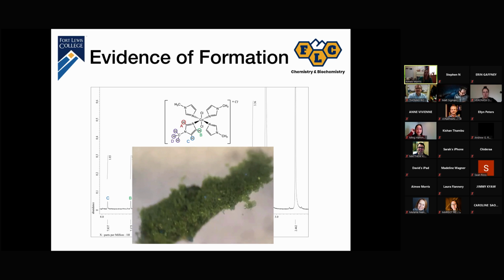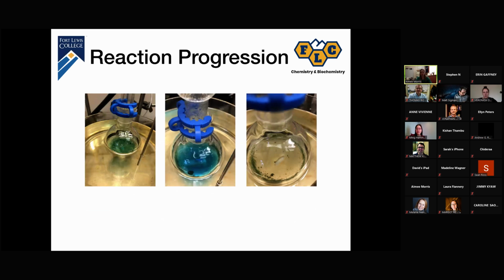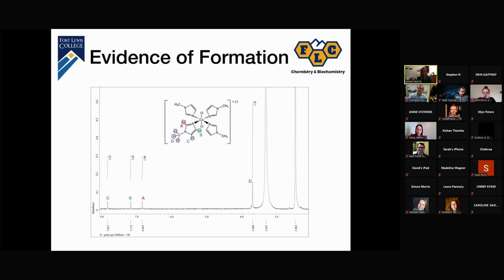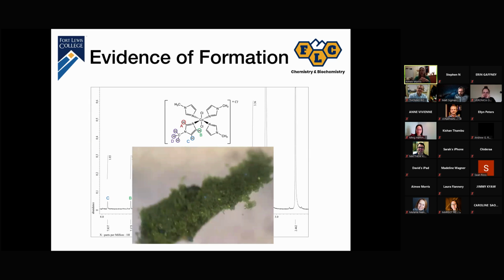And so this is a beautiful reaction, by the way, and students love to run reactions in my lab because they're highly colored. The very first round bottom you're seeing, the cobalt pyridine complex that we start with, is a very glittery green product. We dissolve that with a little bit of heat and methyl isobutyl ketone. During the course of the reflux, we see a color change and we see a bluish color, which always makes me nervous because that usually implies reduction might be happening. And at the end of the reflux, it goes back to colorless and we get a new formation of a green product. But I just showed you that formation of the green product, which isn't completely pure by NMR. And we also see some different coloration within the crystals.